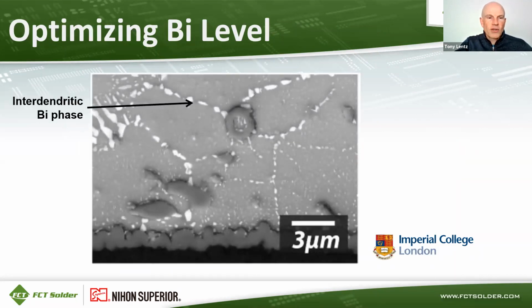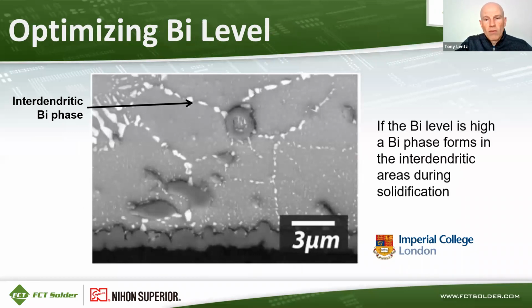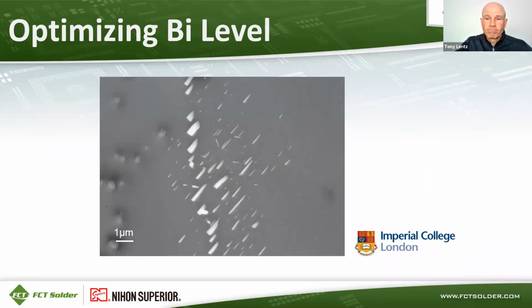Here's a cross section that shows some of the bismuth phase that has precipitated out, and it tends to precipitate out along the interdendritic boundaries. And then we also have the Cu6Sn5 phases shown in the same cross section. So that happens if the bismuth level is too high. So the ideal high reliability solder would have bismuth fully dissolved in solution for solid solution strengthening as a more stable mechanism.